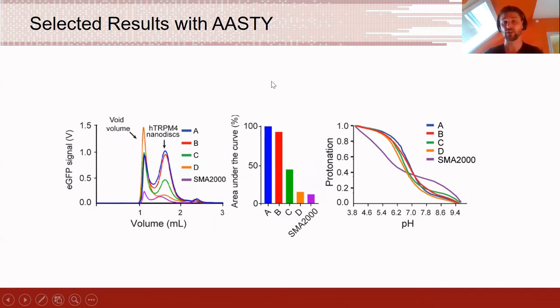And now this is because of the dependency of deprotonating the second acid that's right next to the first acid. So the SMA 2000, as I understand it, works best around a pH of 8.3. So here you have some of the second protons of the acids being deprotonated.